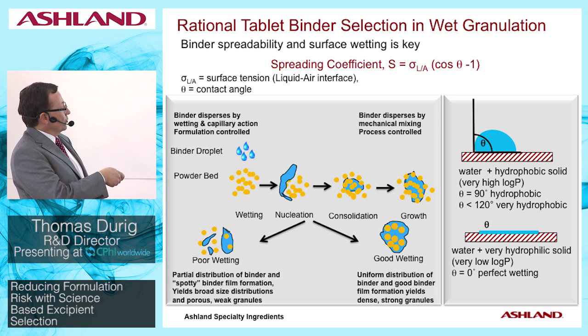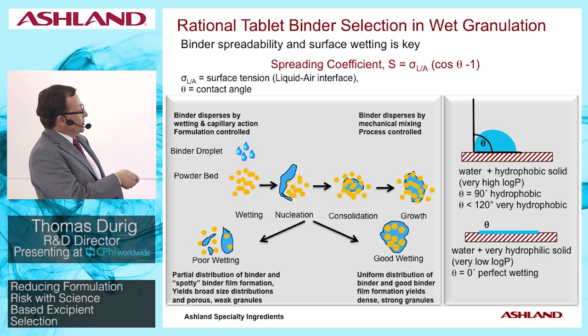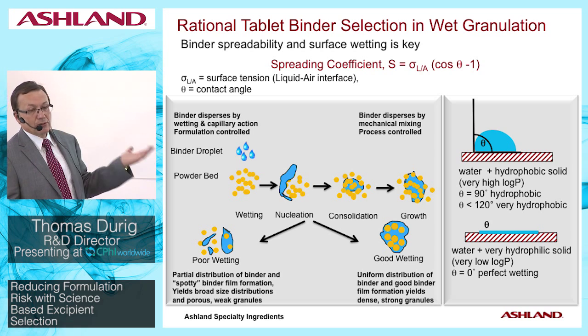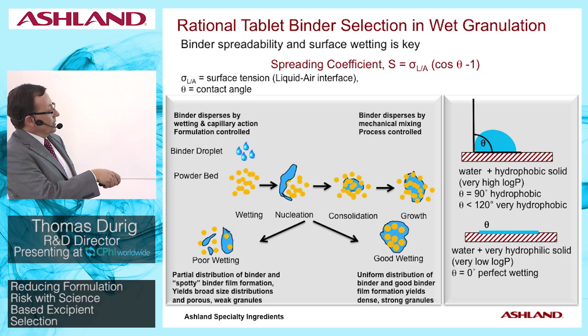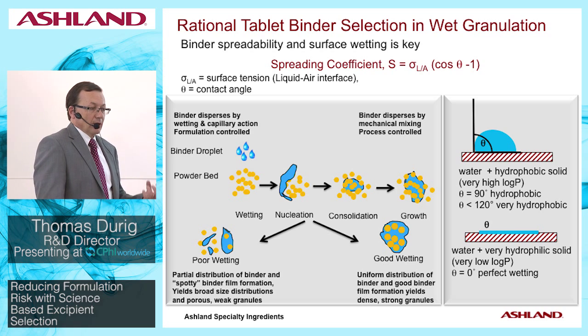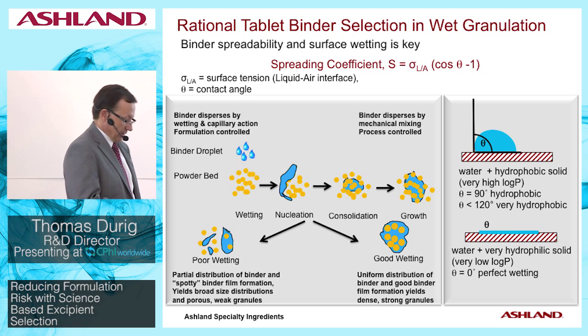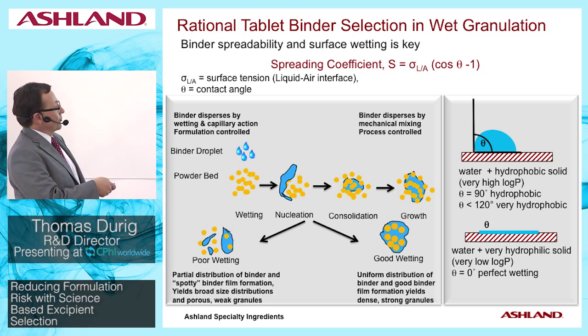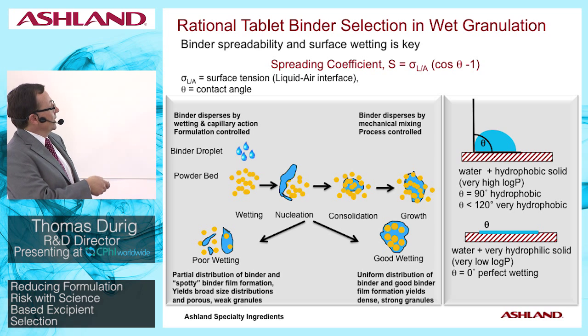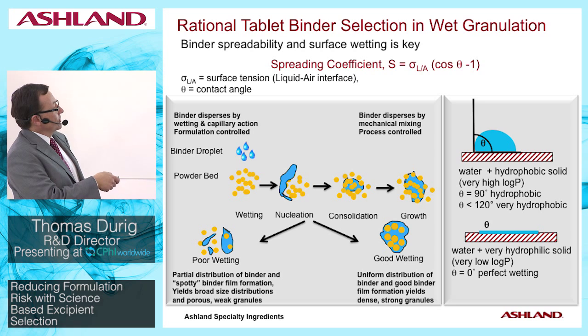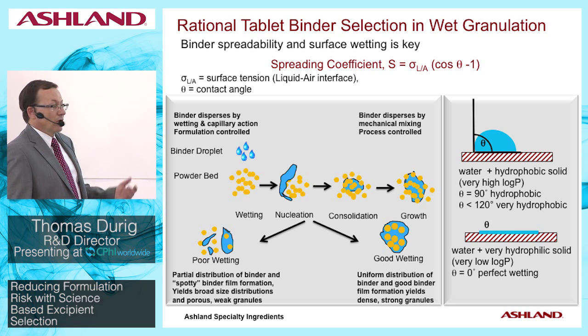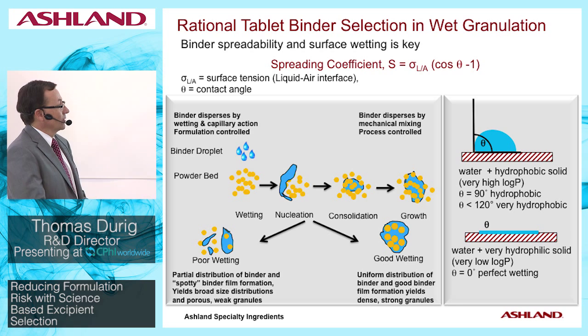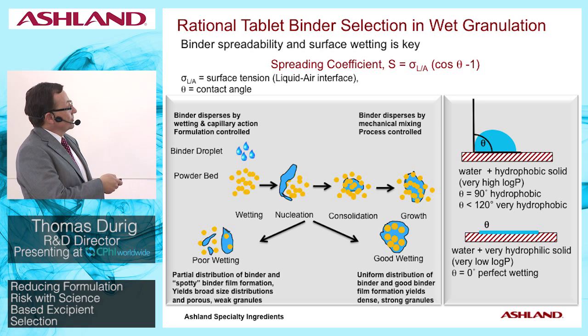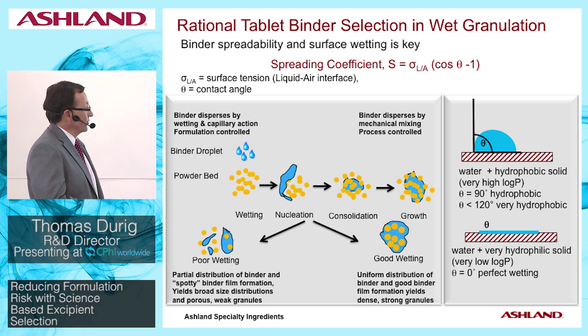On the other hand, if we have good wetting, if the binder solution is chosen such that it has good wetting of the API, we have this situation here where the contact angle is close to 0, and you have good contact between the binder solution and the API, resulting in homogeneous and denser granule formation, resulting in strong granules. This ability of the binder to wet and spread over the powder bed can be measured as the spreading coefficient, which here you can see in this equation is a function of surface tension as well as the contact angle. So it's the surface tension of the binder solution and the contact angle on the API surface.